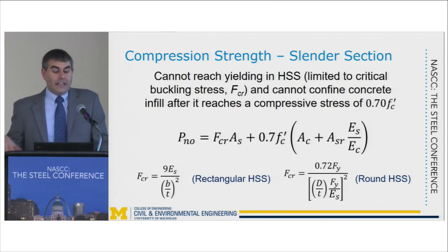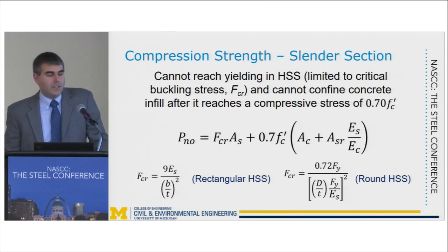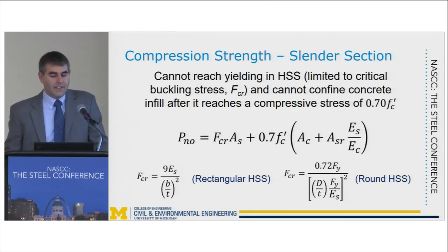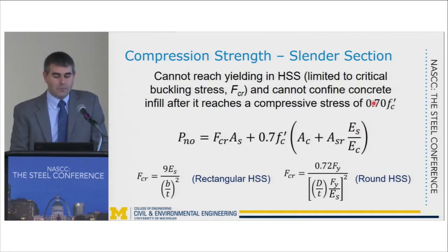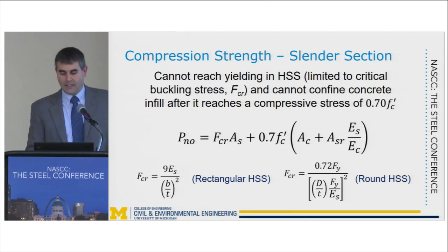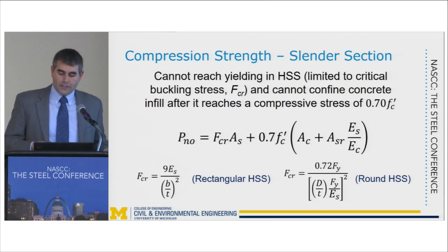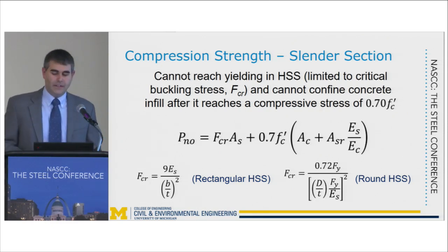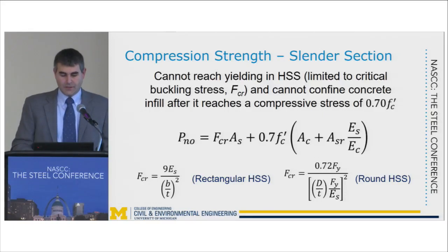Now, for slender sections, you cannot actually reach yielding in the HSS member, so it's limited from the steel side of things to the critical buckling stress. And again, you also can't confine the concrete, so you're limiting that stress to 0.7 F prime C. So you can see the equation for the zero length strength is F critical A sub S now for the steel component, where you're going to use either this equation here for rectangular hollow structural sections or this equation here for round sections. And then the concrete side of the equation is actually the same as what we use for non-compact sections.